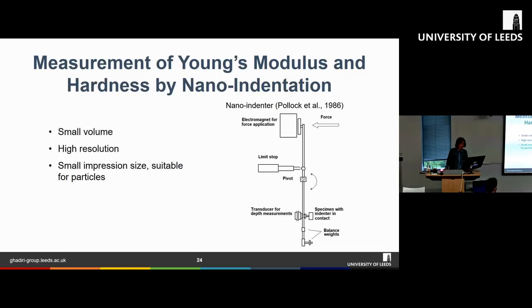We apply a force by electromagnet. Essentially, you apply current through this electromagnet, and then this coil here gets pulled towards the electromagnet. At the middle here we have a pivot, and as a result of this pulling force towards the electromagnet, the indenter gets pushed towards the surface of your specimen. To measure the depth, we have a transducer here, and the change of the distance between this plate results in a change of the capacitance. By measuring the capacitance, we can correlate how much depth the indenter has penetrated through the surface of the material.